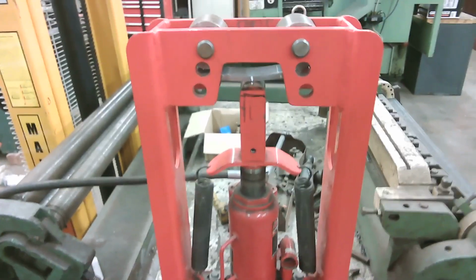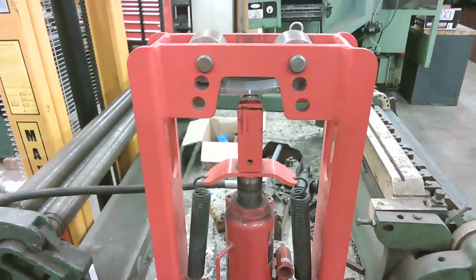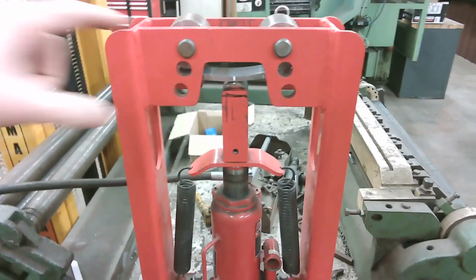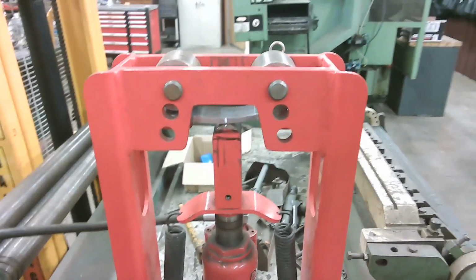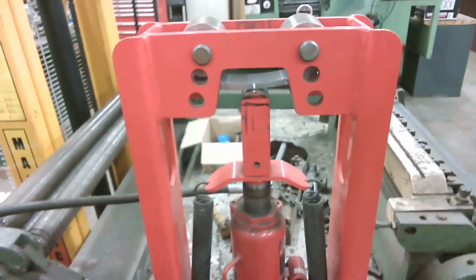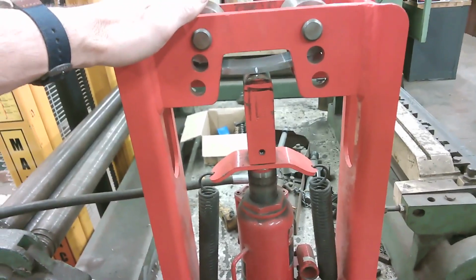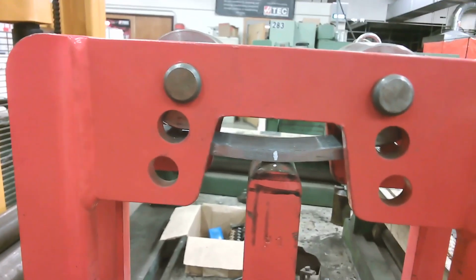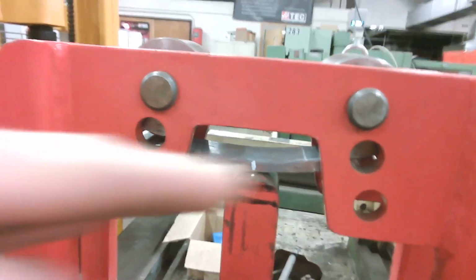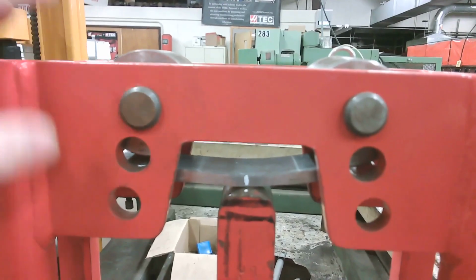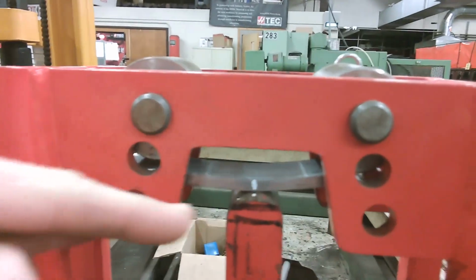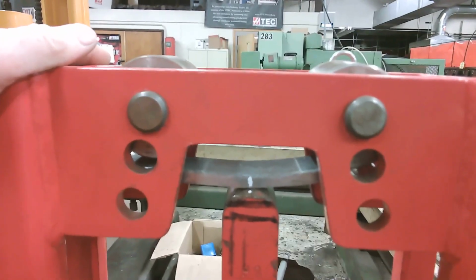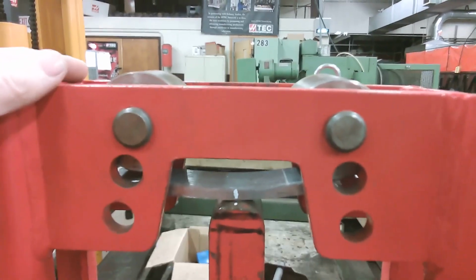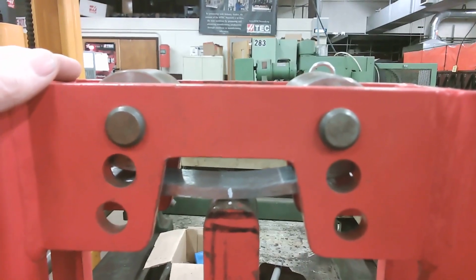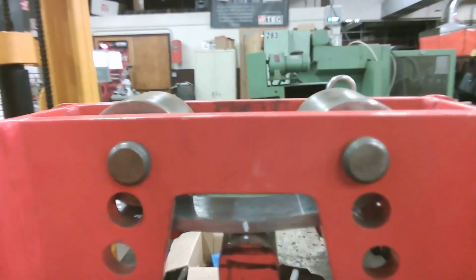Okay, this is our bend tester. Pretty straightforward. We've got a roller. There are different positions set up for the roller depending on the thickness of metal you're bending, but this one happens to be set up for 3/8 plate. I did make a mark at the center of the piece, and you can see based on the bend of the part already that this would be the face. The plate warps a little bit towards the face. The sides pull up. So we're doing a face bend. I've actually already done the root bend on this, so I'll show you both of them when we're done. Here we go.